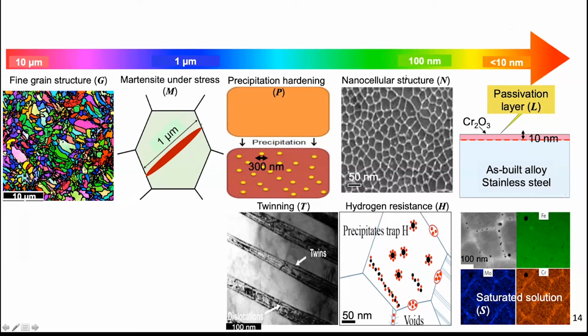Last are these two very small features, which is a passivation layer. The fact that when I print, I can promote the existence of an oxide layer that impedes oxidation, and last, the presence of a saturated solution. The fact that 3D printing, because it's so fast, allows me to saturate with solutes an alloy in ways that otherwise would not happen, and this can give us significant strengthening as well.